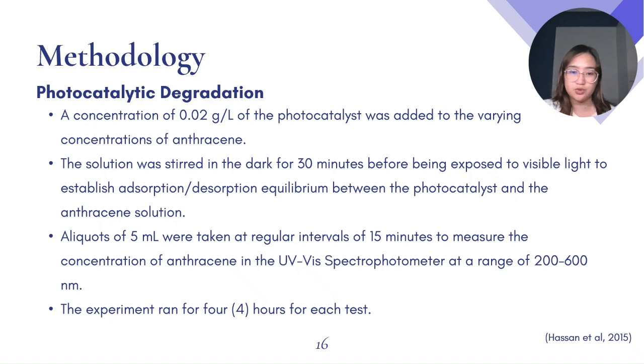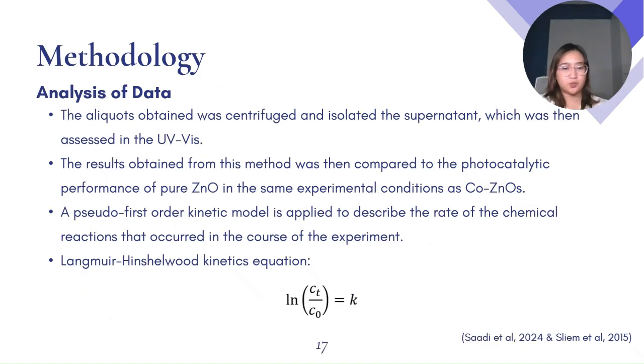A concentration of 0.02 gram per liter of the photocatalyst was added to the varying concentrations of anthracene. The solution was stirred in the dark for 30 minutes before being exposed to visible light to establish adsorption-desorption equilibrium between the photocatalyst and the anthracene solution. Aliquots of 5 ml were taken at regular intervals of 15 minutes to measure the concentration of anthracene in the UV-Vis spectrophotometer at a range of 200 to 600 nanometers. The experiment ran for 4 hours for each test. The aliquots obtained were centrifuged and isolated to supernatant, which was then assessed in the UV-Vis. The results obtained from this method were then compared to the photocatalytic performance of pure zinc oxide under the same experimental conditions as Co-ZnO.